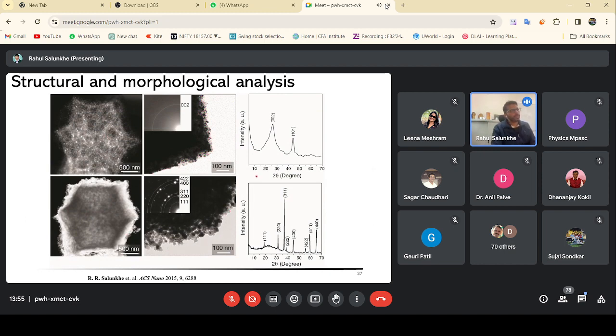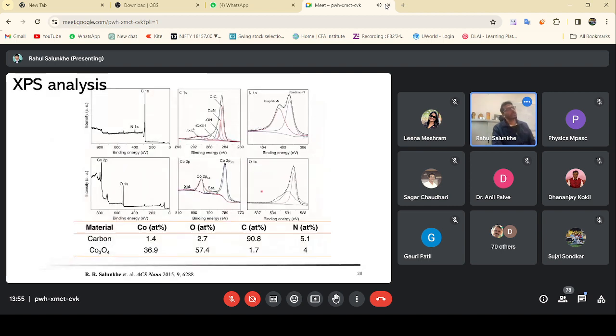So this is a typical structural analysis. We can see that this is a selected area electron diffraction pattern, and we can see that two peaks associated with graphitic carbon can be observed. Whereas in case of the metal oxide, we can see different peaks associated with the metal oxides in HRTEM as well as the XRD analysis. Again, several supporting studies have been carried out to define the ratios of cobalt, oxygen, carbon, and nitrogen in this carbon and cobalt oxide.